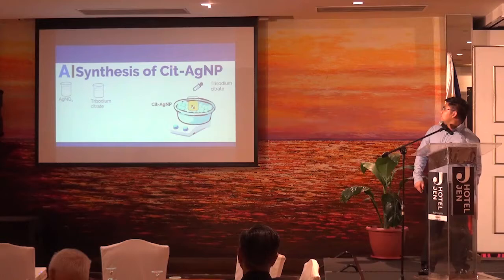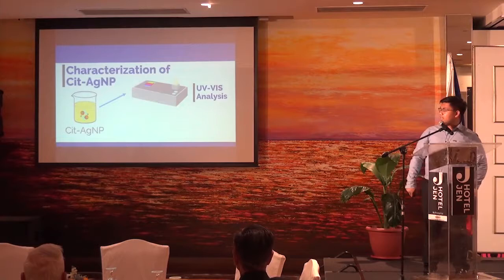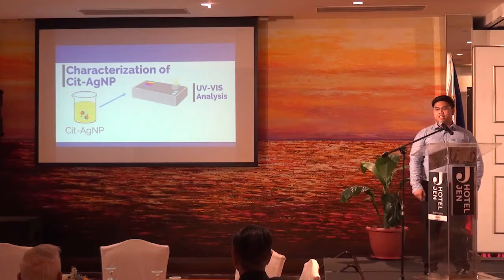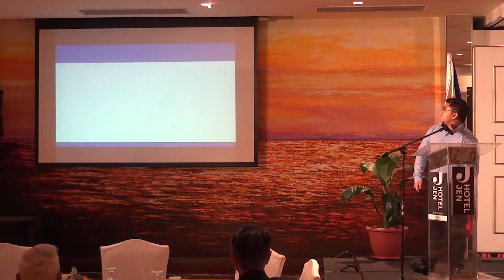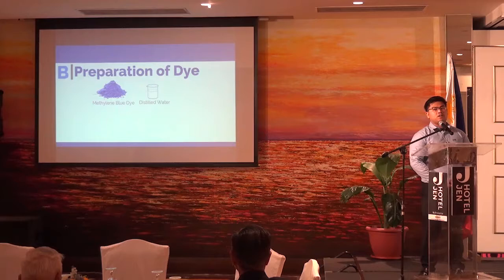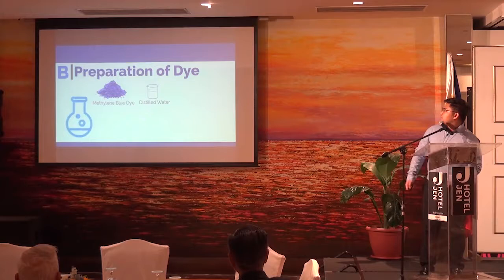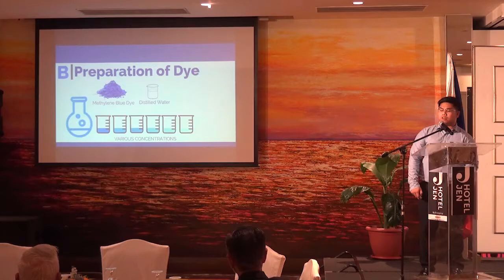Now that we have produced citrate-stabilized silver nanoparticles, we verify them using UV-Vis analysis to test for absorbance, and also TEM analysis to test for morphological properties. Next is the preparation of dyes — in order to identify the concentration of our dyes through time for our test, I prepared several concentrations of methylene blue to graph absorbance versus concentration.